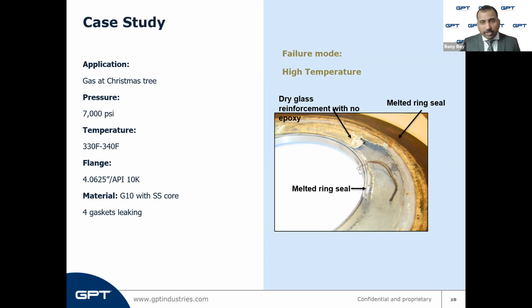Now, the G10 glass reinforced epoxy, GRE, near the bore on both sides of the gasket was very dry and brittle, which is consistent with the epoxy binder being driven out of the glass fabric by the high temperature. This leaves the G10 very weak and brittle and can allow the seals to creep, especially at these temperatures and pressures. The drying of the glass mesh, that is the absence of epoxy, became much less severe away from the bore. That tells us the inner portions of the gasket experienced higher temperatures than the outer portions. And the upper limit of G10 is 302 degrees Fahrenheit or 150 degrees Celsius. So this was not the correct choice for this application, eventually leading to a blowout.